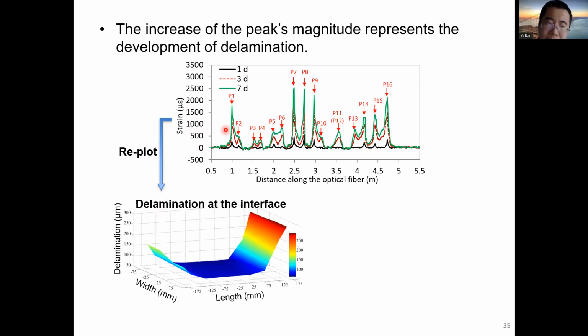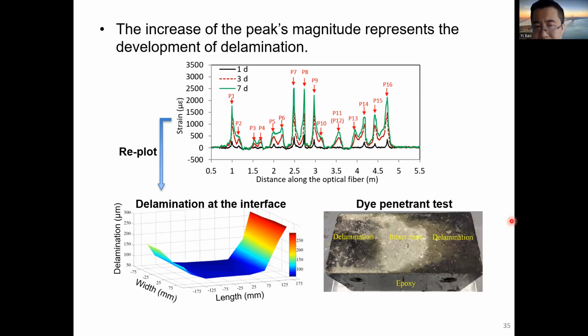Then we can separate this strain distribution into different segments and then replot that to show the delamination condition. So in this figure, the red color refers to delamination. You can see that delamination occurred at the two ends of this specimen. And in the middle, blue color shows no delamination. And this delamination estimation result was validated by a dye penetrant testing. So we immersed the specimen in dye solution, and after a certain time, we removed the overlay, and then we could visualize the interface condition.